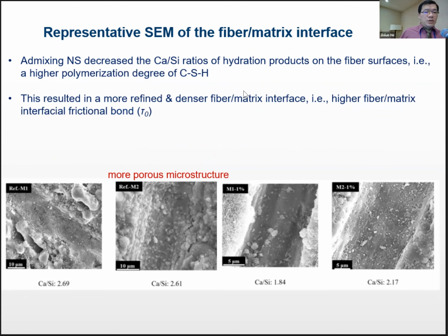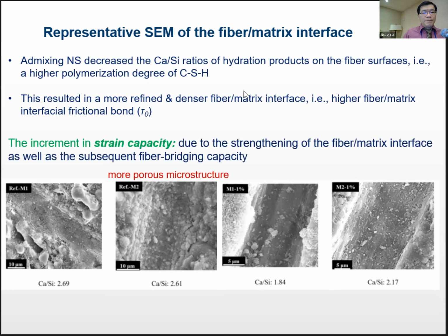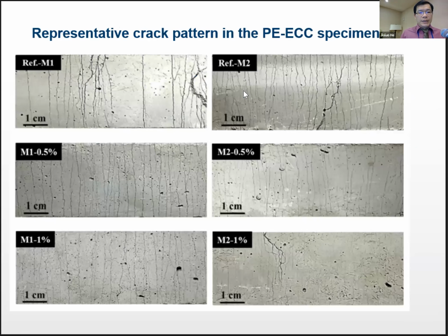The presence of nanosilica, you look under the microscope, for instance, without nanosilica, you're seeing a coarser, more porous microstructure. On the right-hand side, when you add 1% nanosilica, you're seeing a denser microstructure. This translates to a higher friction bond between the fiber and the matrix, which is called tau 0. So the idea is that the strain capacity improvement was due to the denser microstructure and the better bond. Anyway, you're seeing this kind of behavior, again, micro cracks instead of wider cracks.